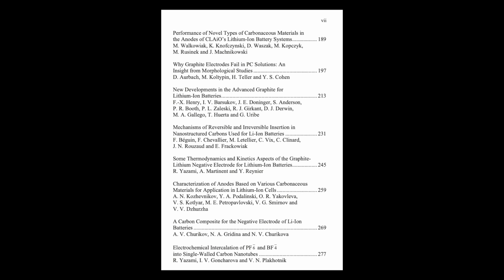Okay. But the other huge factor, highlighted over and over, is that initial irreversible capacity loss. The capacity you lose in cycle 1 and never get back? Precisely. That's the lithium used up forming the SEI and maybe other initial side reactions. Minimizing that loss is a massive focus because it directly impacts the battery's usable energy from day one.